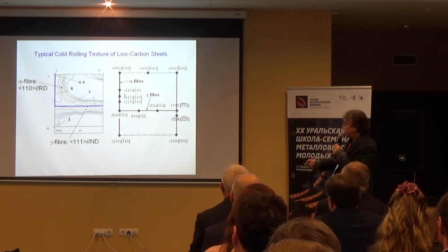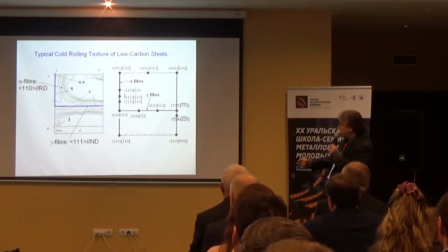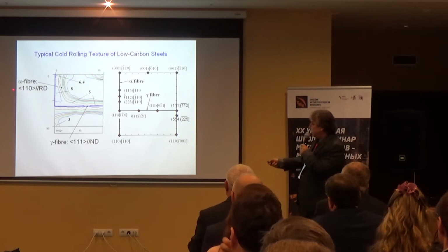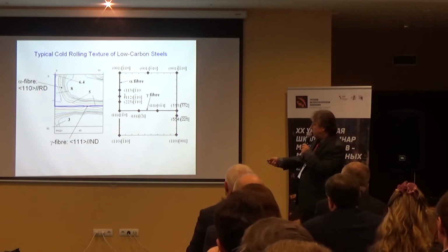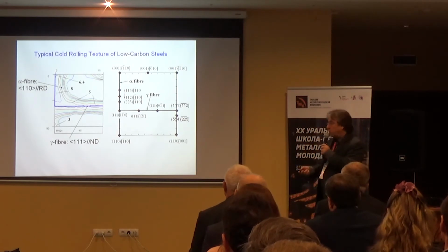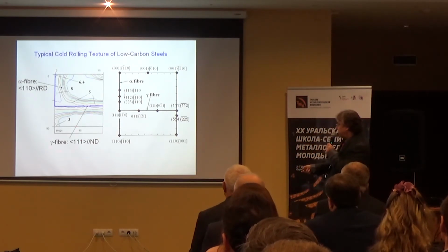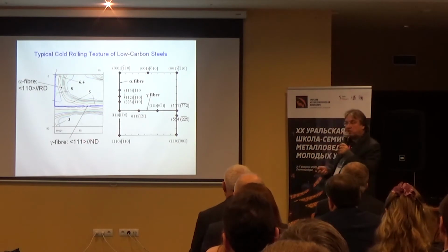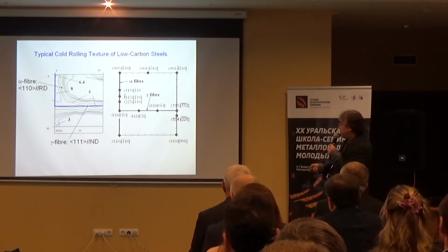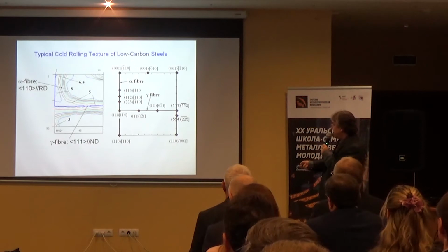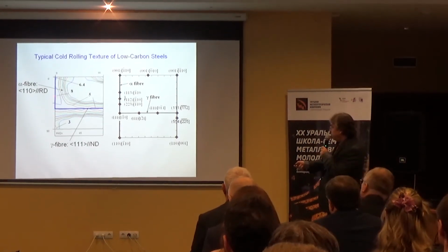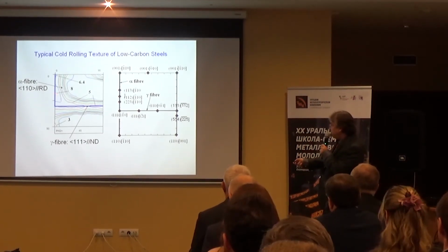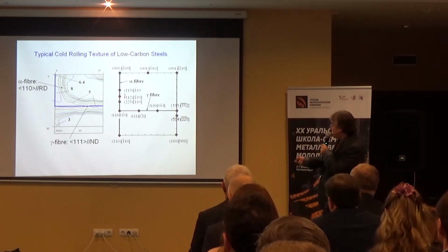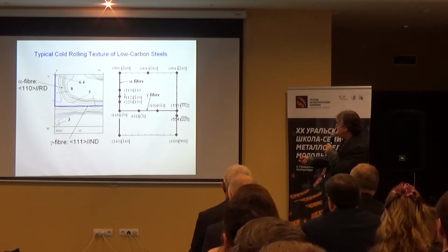We have an alpha fiber, which is the set of orientations that have the 110 direction parallel to the rolling direction. And we also have the gamma fiber, which has the 111 orientations parallel to the normal direction. Here you can see that, for example, there is a maximum here on the alpha fiber of 8, and this maximum more or less is situated at this component, 112 minus 110.